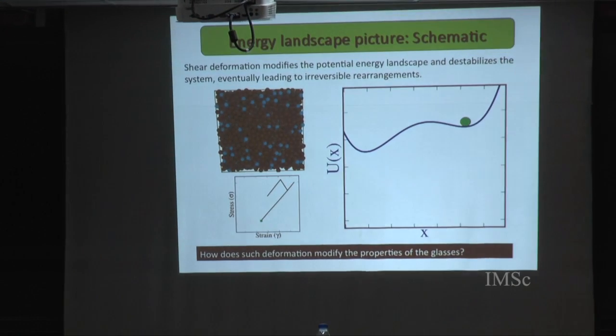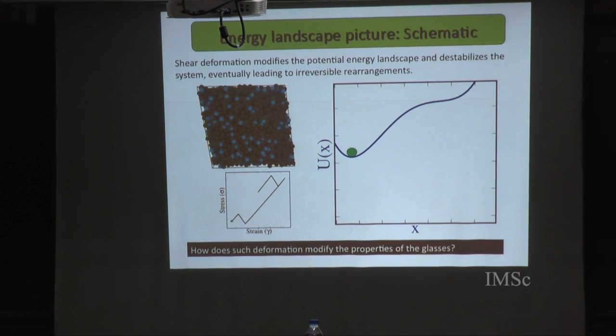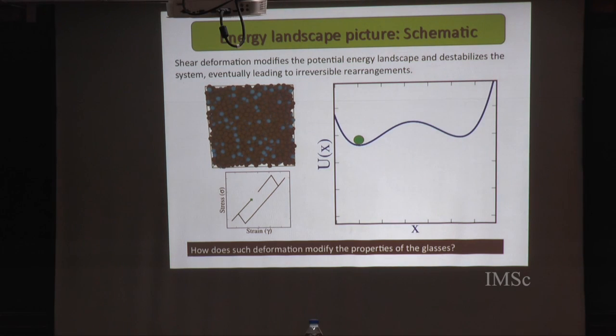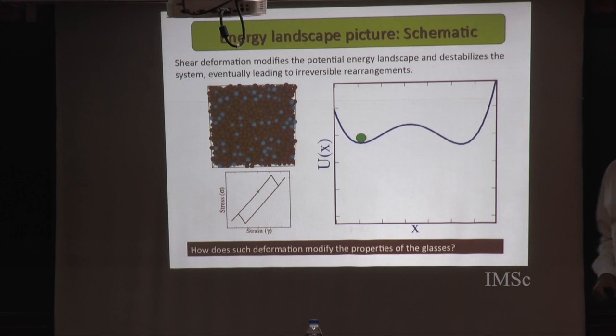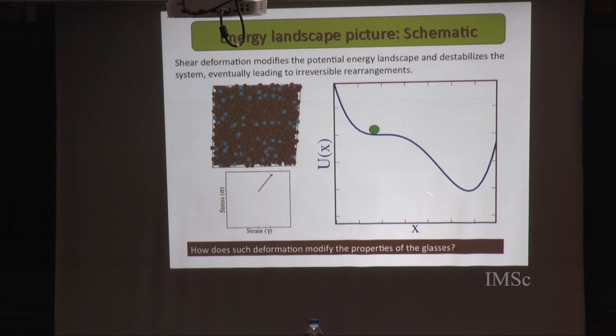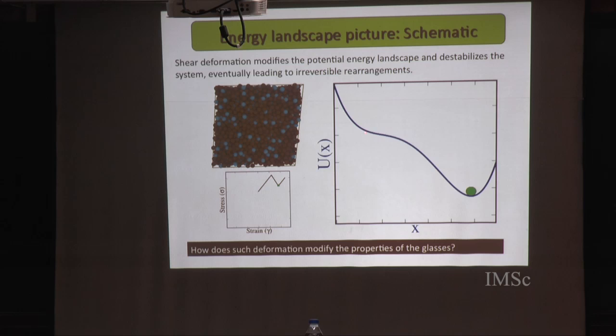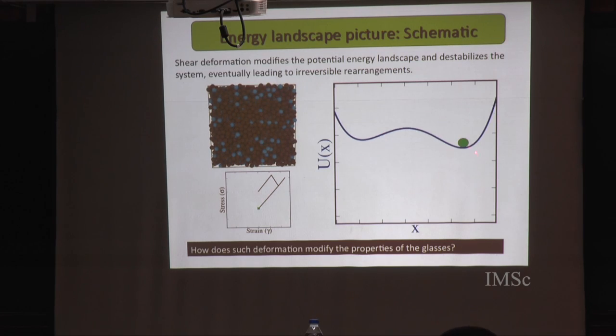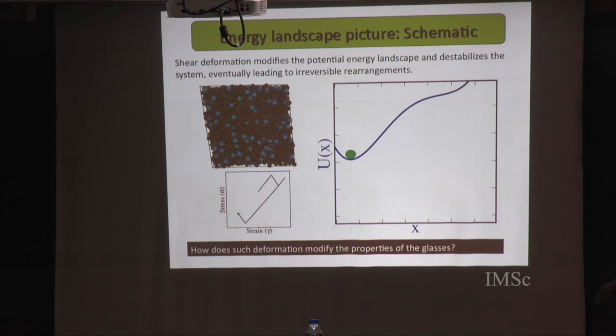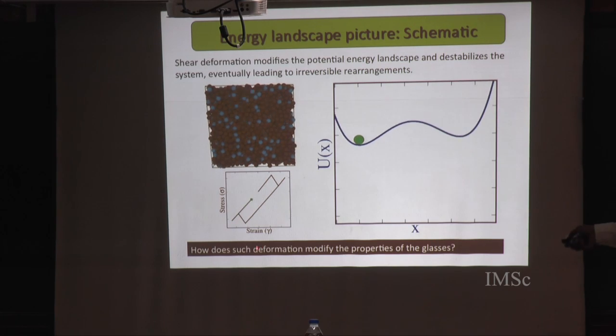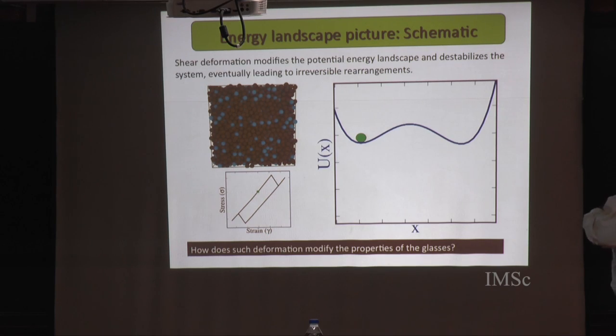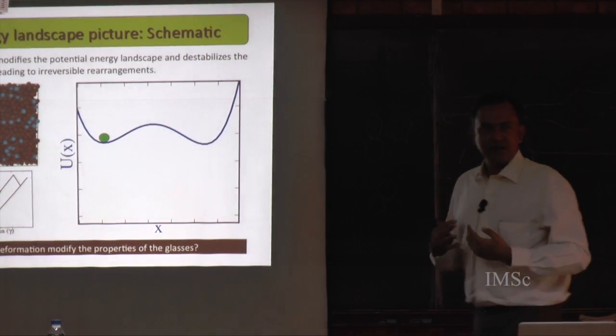So here is a schematic of what we do. If I imagine a two-dimensional energy surface, this is the basic unit of irreversible transformation. If I start from here, as I apply external deformation, the energy landscape gets modified till the minimum I'm sitting in becomes unstable, and I make a discontinuous transition to another energy minimum. The important thing is, in order to make the transition back, I have to strain back to a much larger degree than I initially started with.